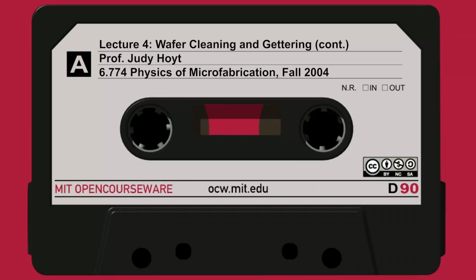Titanium and moly, molybdenum, are actually kind of problems. They're primarily substitutional, but they have relatively slow diffusion rates, whether they're substitutional or interstitial. So Ti and moly are going to be hard to getter because their diffusion rates are not very large. So to get them all the way to the back of the wafer is going to take a long time. So it's just not very effective.